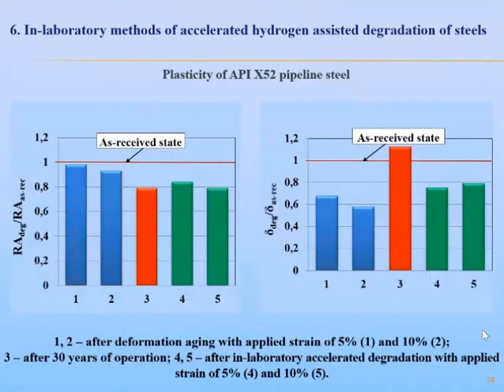And here you can see a comparison of change in plasticity characteristics of steel after its treatment using these degradation methods. In the middle is the operated pipeline steel, on the left the result of the known method of deformation aging with two levels of plastic deformation, 5 and 10%, and on the right using the developed method. So it's obvious that the developed method provides better conformity to the real steel state after operation.